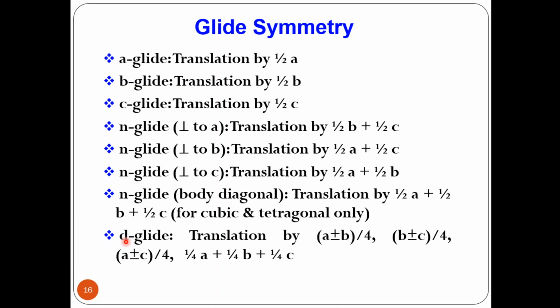D glide, D is derived from the term diamond, and this sort of glide takes place along a plus or minus b over 4. This should be the magnitude. This 1 over 4, the quarter, is very important, and because of this quarter we say that this is the d glide, the diamond glide. And why is that so? Because the diamond crystal structure consists of face-centered cubic structures such that the two face-centered cubic structures are shifted apart along the body diagonal by 1 over 4 of it. That is why this D is used in here.